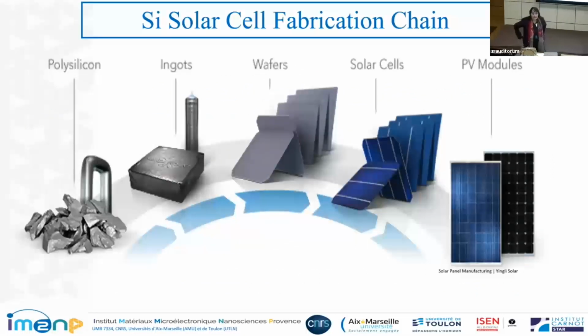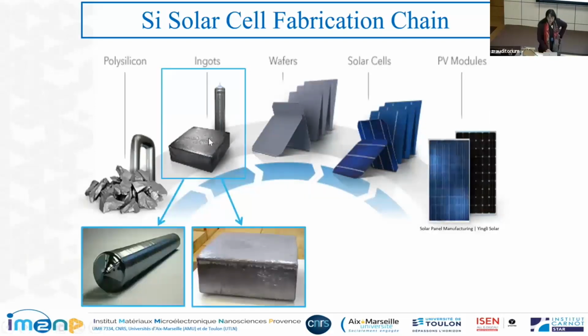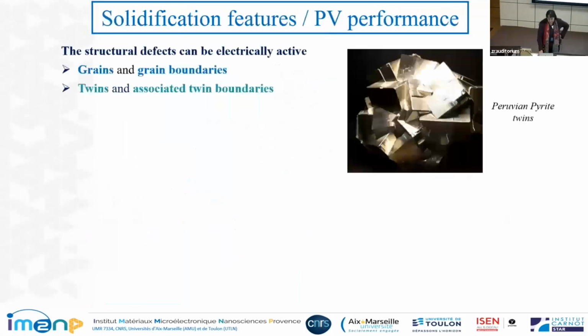So here is the silicon solar cell fabrication chain, from the purification of the material here to the fabrication of the PV modules. And we focus on this step where you fabricate the ingots, which are cut later on. And this is a solidification step. You have several processes that you can use, but basically this is solidification. And during this solidification step, you will create a lot of defects which have different scales, from grains and grain boundaries. You also have twins and associated twin boundaries.